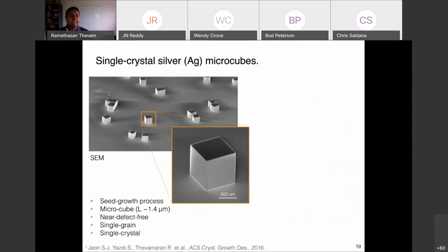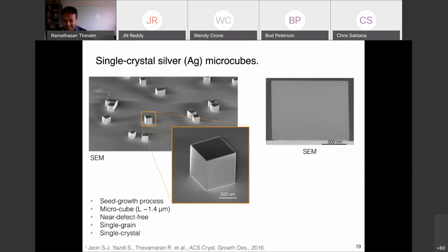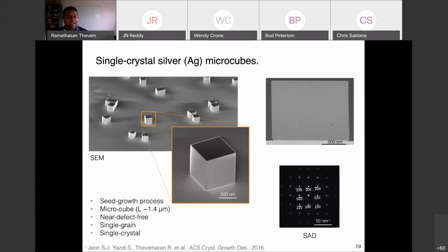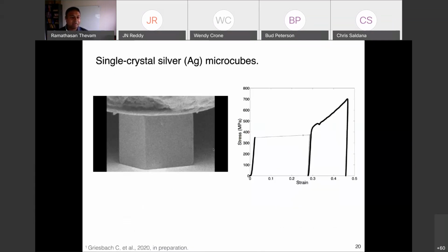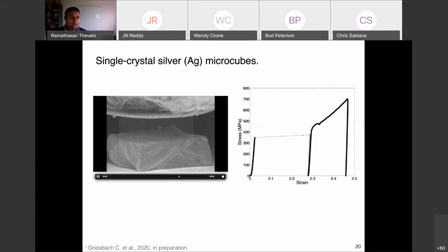To study this, we have taken a single crystal microcube of silver that was fabricated by Sujin Jeon, who is a faculty right now in Korea. So these are single crystals that are defect-free and perfect cubic shape, as you can see. So this gives us a well-posed system to study this problem. If you cut and look at it, it's one single grain. And if you take a diffraction pattern, you can see that it is a face-centered cubic material. So it shows a very nice cubic diffraction in the material. If you take this cube and compress it slowly, as you can see, this is a nanoindenter that is compressing this material. It will compress and suddenly undergo an abrupt strain burst.